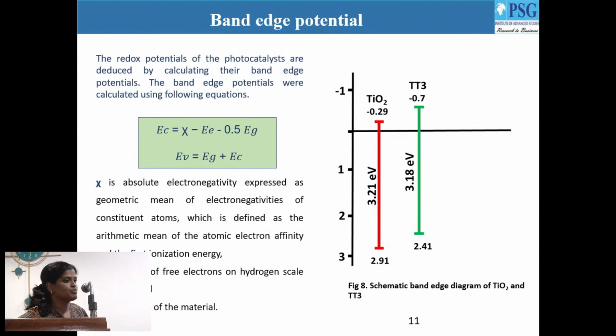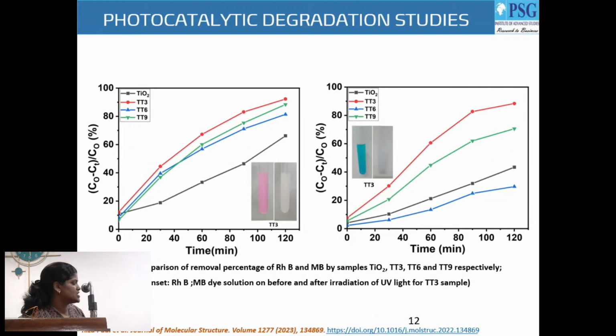This is the band edge potential we have calculated with the equation. Then we have got the conduction band edge potential and valence band edge potential, which confirms the band gap of both the composites. And these are the degradation studies with both rhodamine dye and